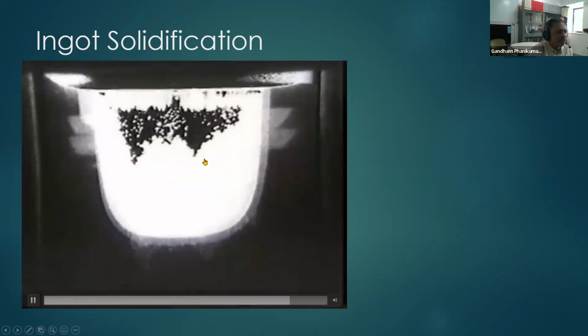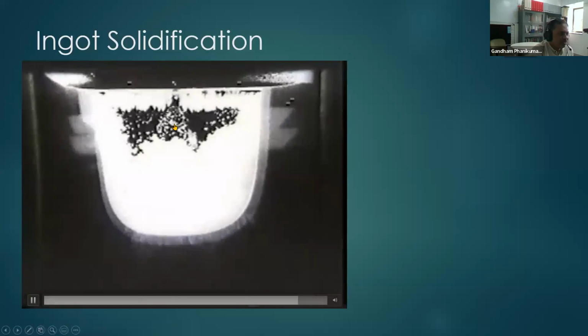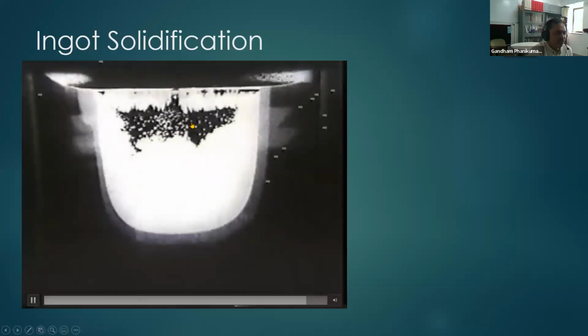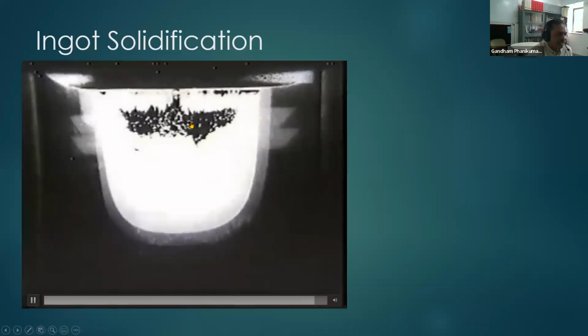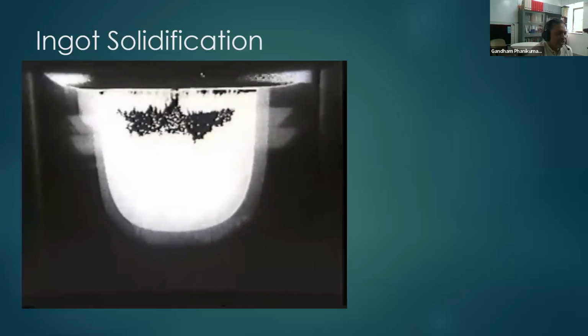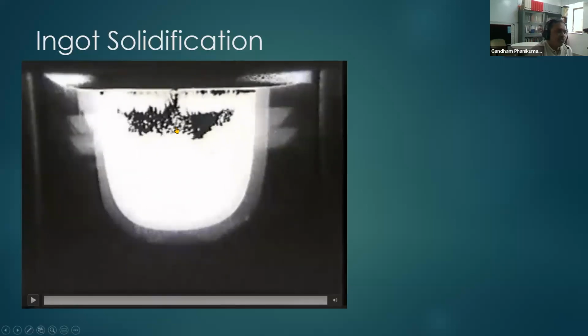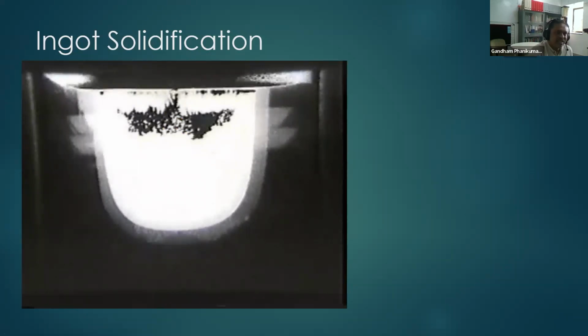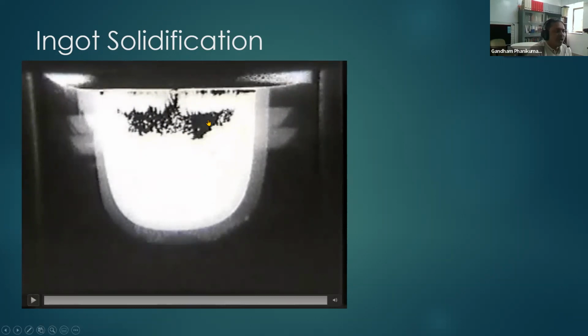Now, as it is going towards finishing, there is some region of the liquid which doesn't fill up the void, and therefore you will have some shrinkage that is happening, and that is also known in casting as a pipe defect, for example. And in the case of laser additive manufacturing, if the powder after melting doesn't fill the entire space, you will have porosity. So the origin of porosity, you can also see here, if it was incomplete melting, and that is one of the regimes that we will see.